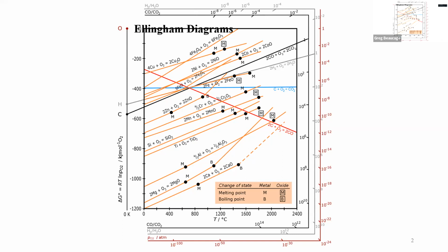So anyway, one way you can easily make silica, SiO2 nanoparticles, is just by burning silicon tetrachloride. You just torch it up, you collect it, you have bag loads of it, or train loads if you want. So what people are doing is they use magnesium. Magnesium's way down here, that's good, and silicon, Si and SiO2 is way up here. That means at almost any temperature you can reduce silica with magnesium metal. So if you can get magnesium metal, you can make nanoparticle SiO2, and then you can reduce it with Mg.